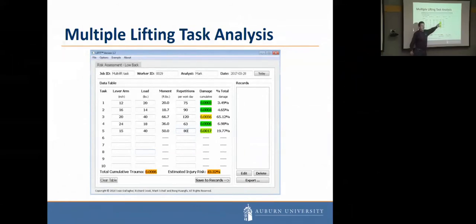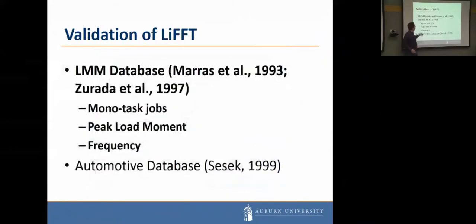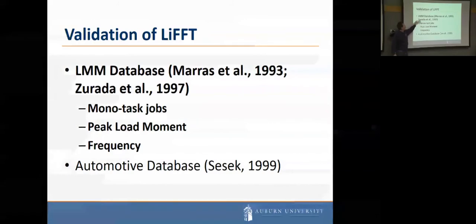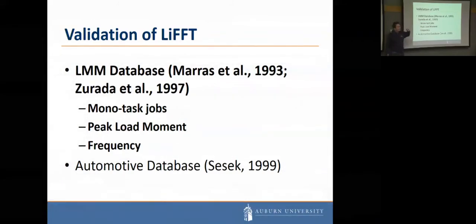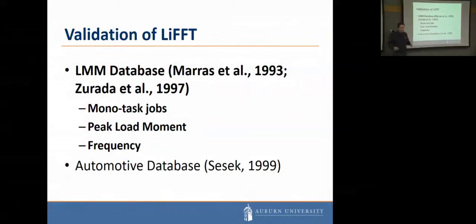So the green is fairly safe, then yellow is worse, and orange is worse, and red is the worst. Okay, so at any rate, we validated this tool, and we think it's pretty simple. You can go through a plant pretty quickly and get all your jobs done on this. So we tested against a database that was developed for the lumbar motion monitor, which is a goniometer that you strap to your back, and it follows your motions. But they had what we needed.